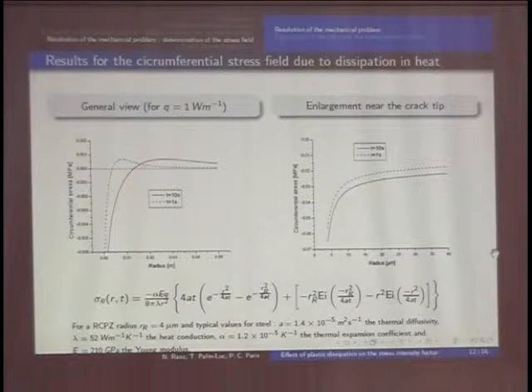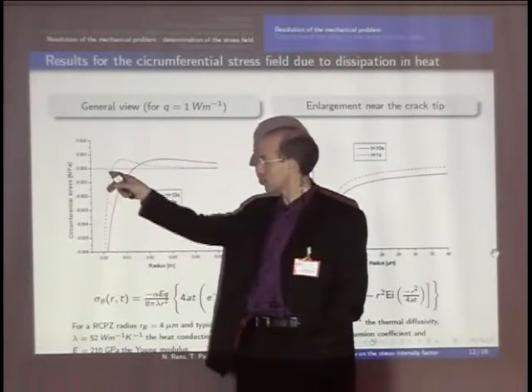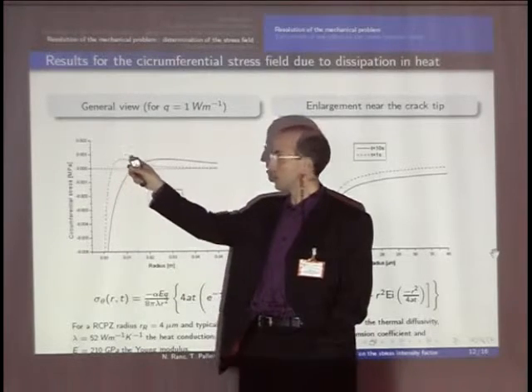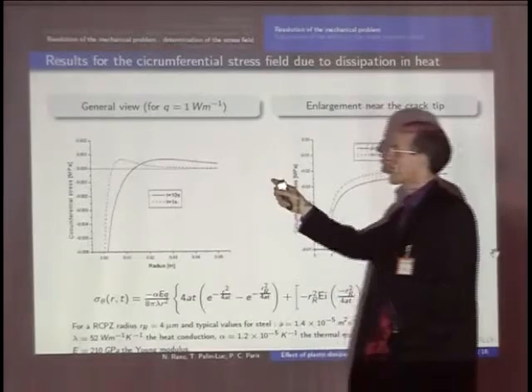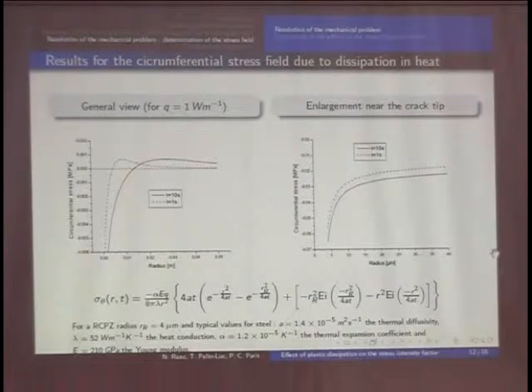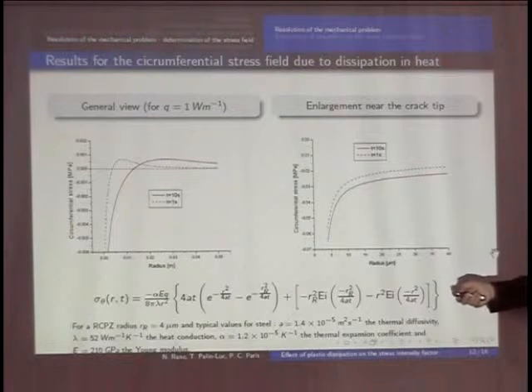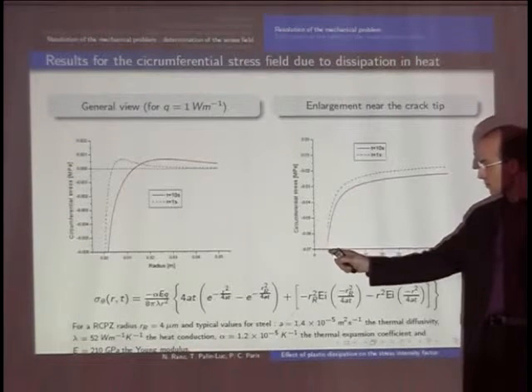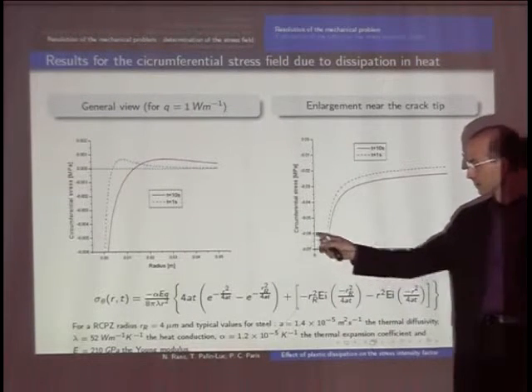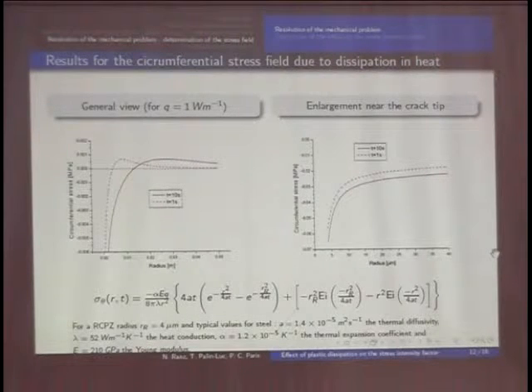Now, if we look at the circumferential stress, we can see approximately the same analytical equation with some difference with the sign, but these differences are important due to the following consequence. The crack tip is always here. You can see that the circumferential stress is negative around the crack tip, and after there is a small peak in tension for equilibrium, and then it goes to 0 because of the very large scale of the material in this case. If we focus in this area near the crack tip, we see that there is a finite value around 4 micrometers, because 4 micrometers is the radius of the reverse cyclic plastic zone, which is here. So in this case, we have this stress field.